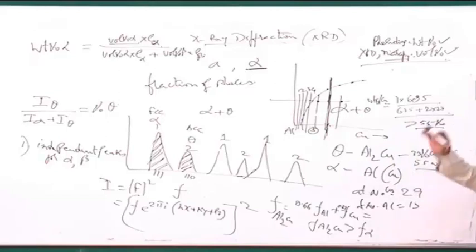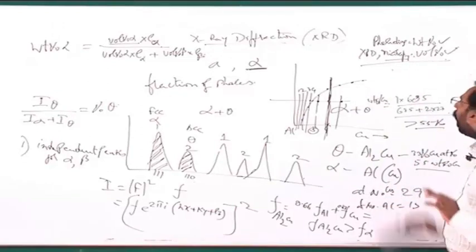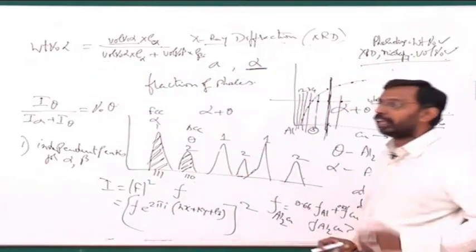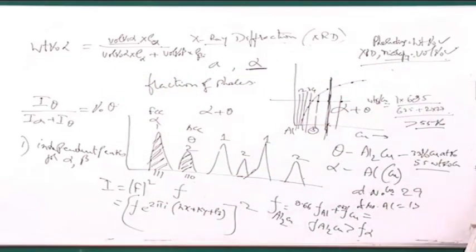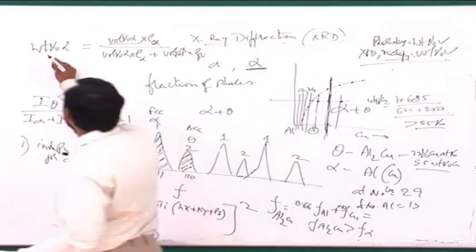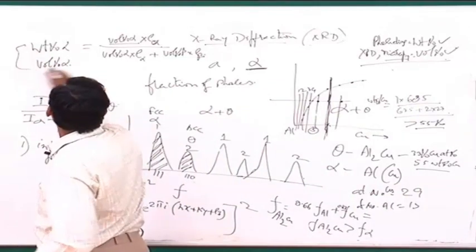It will only give you area percent, and doing image analysis and making some assumptions, we can convert area percent to volume percent. And from that volume percent, I have to convert it to weight percent, then compare, then only you can say this. Under certain special conditions, we can consider weight percent to be equivalent to volume percent without doing all these calculations.